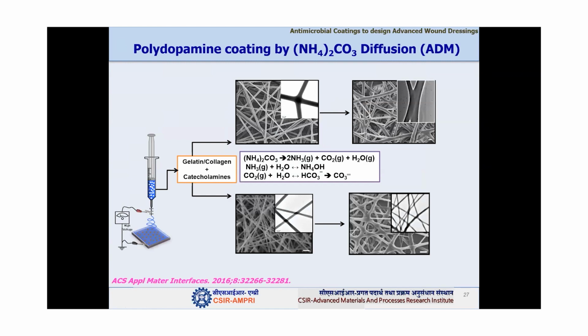So this is how we then did our crosslinking. This is the electrospinning, as I mentioned to you. Here we are putting the potential, and this is gelatin nanofibers, and the lower picture is for the collagen nanofibers. So these are two different proteins. You can see the nanofibers here. So when we did the spinning, during the spinning itself, we put in the dopamine. So this solution is basically gelatin plus dopamine, and then we spin it. So here is after spinning. You can see here, as we have put in the dopamine, the fibers got merged at the junctions. In the same way you can see here also. In collagen also, we got some binding at the interface.